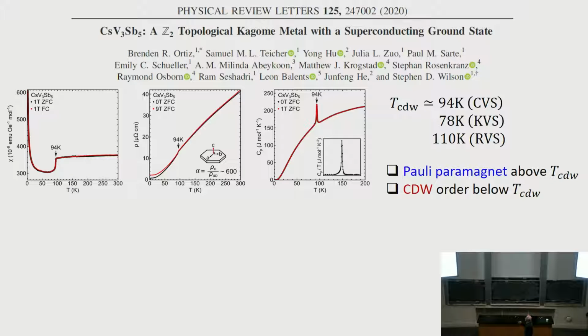So what happens here is they all undergo a CDW transition as you lower the temperature, around 100 Kelvin. And what's really interesting is this is the magnetic susceptibility.